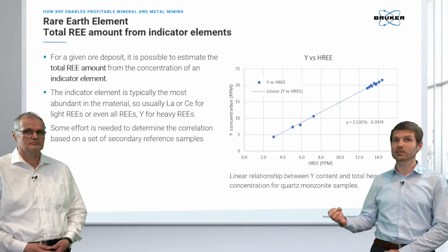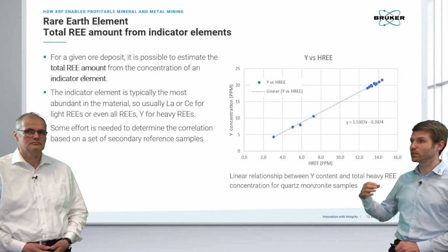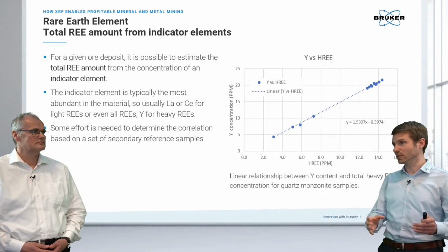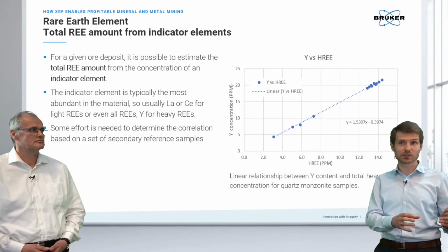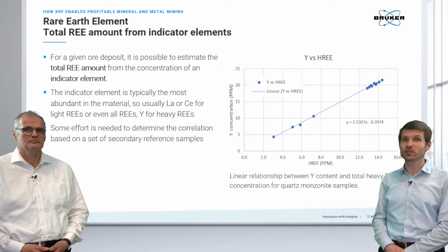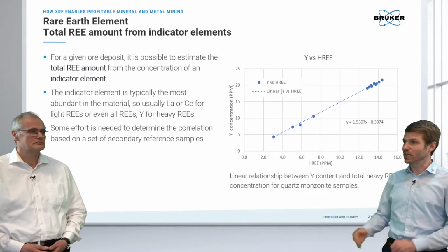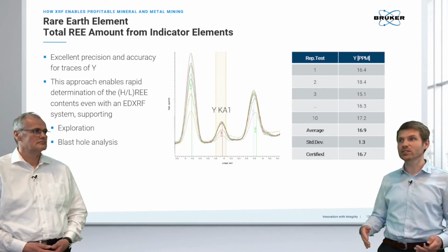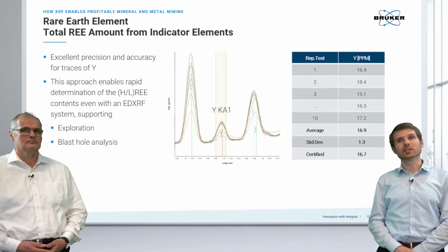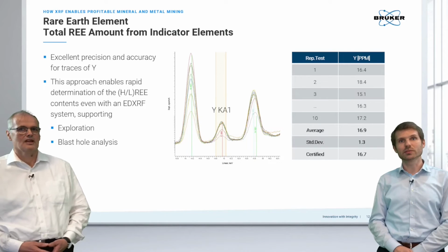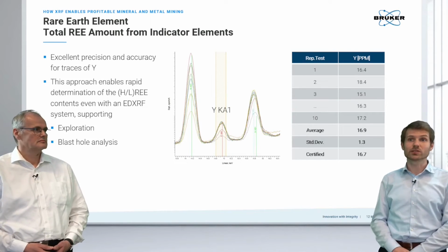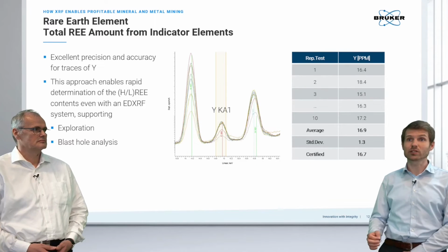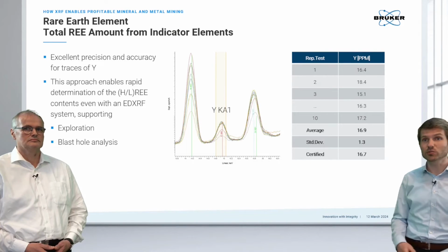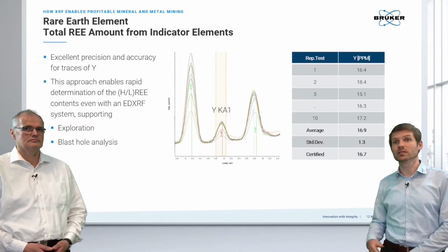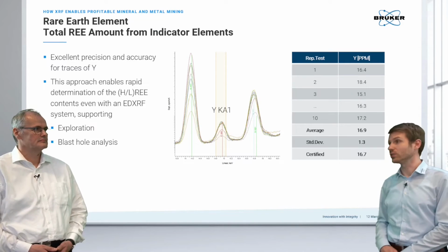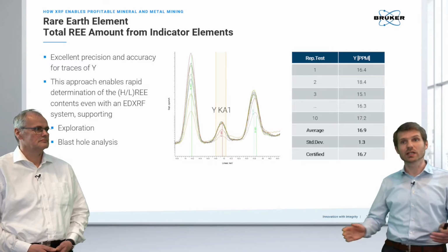So we can, for example, say that yttrium is proportional, for a given type of material, given region, given deposit, to the concentration of total heavy rare earth elements. And this little workaround allows us to actually determine the heavy rare earth elements with a simple energy dispersive system like the S2 Puma quite accurately. So here we see just the measurement results for yttrium in the relatively lower ppm range, so 17 ppm, and we see really a high precision.